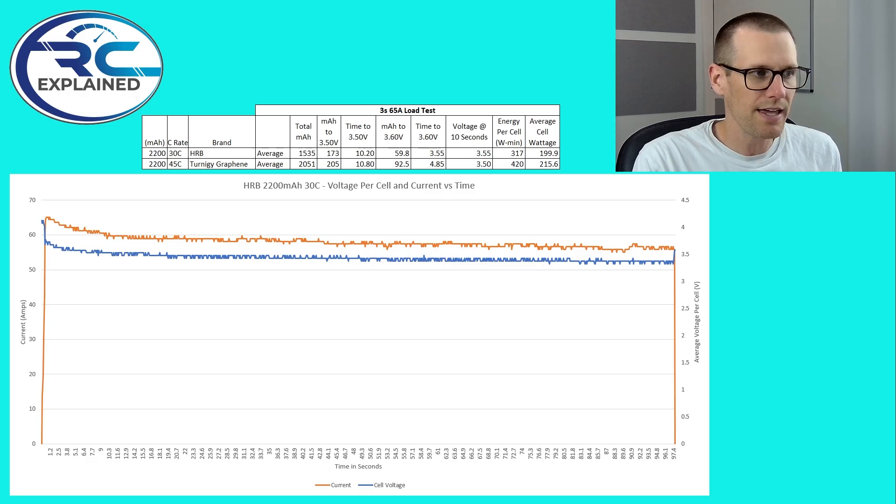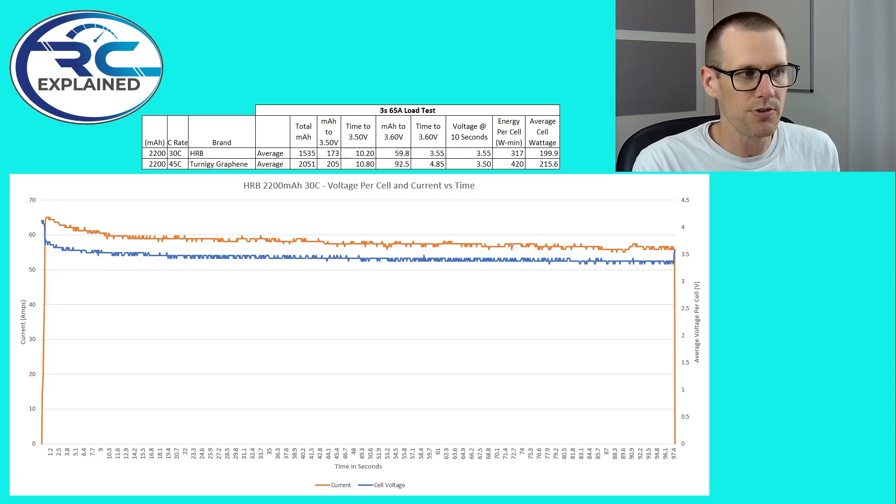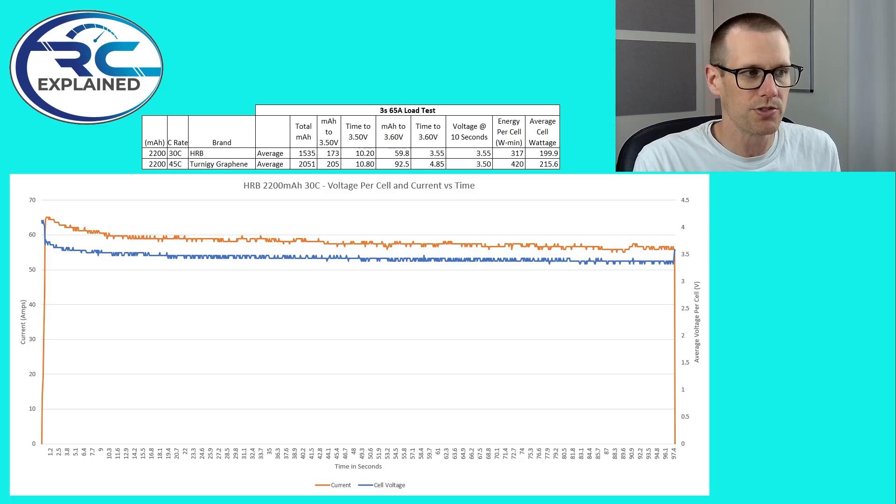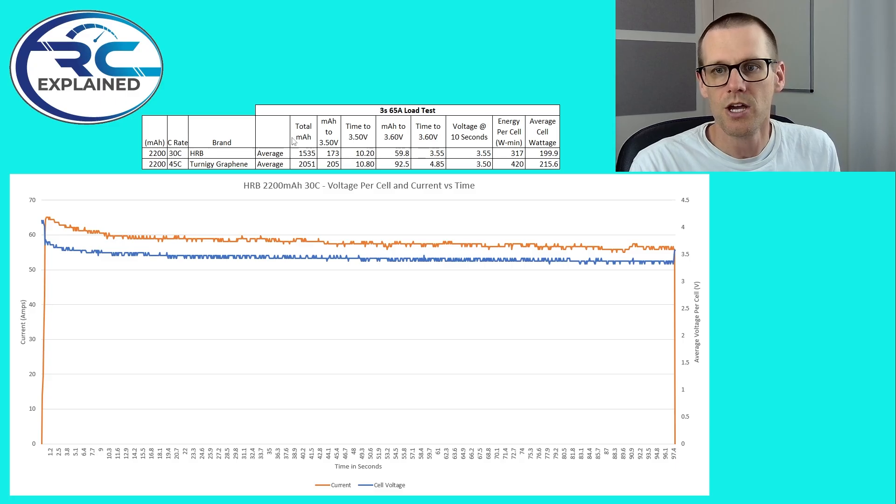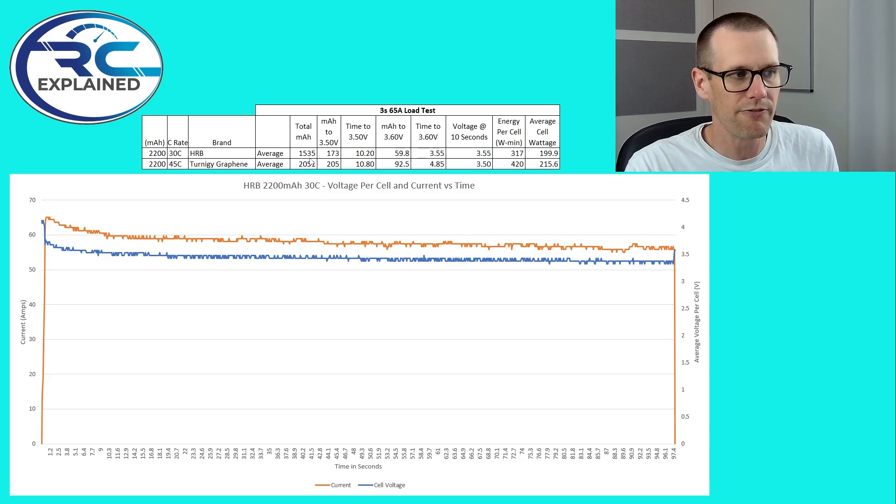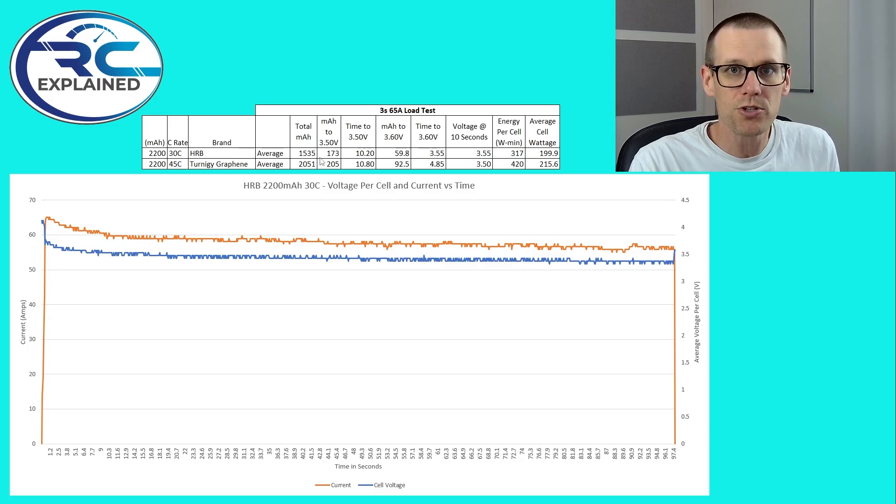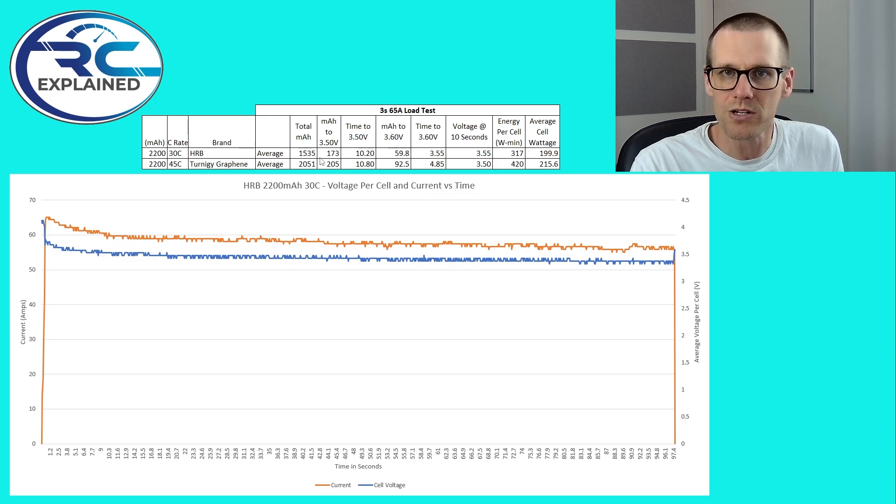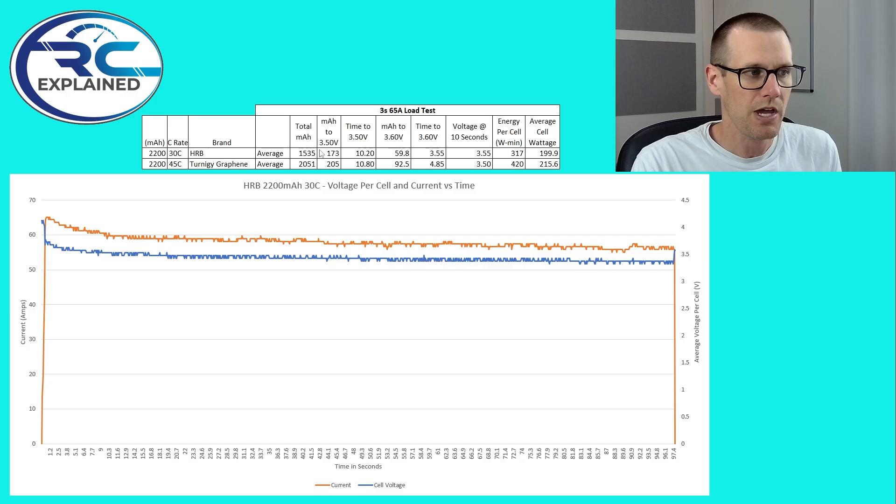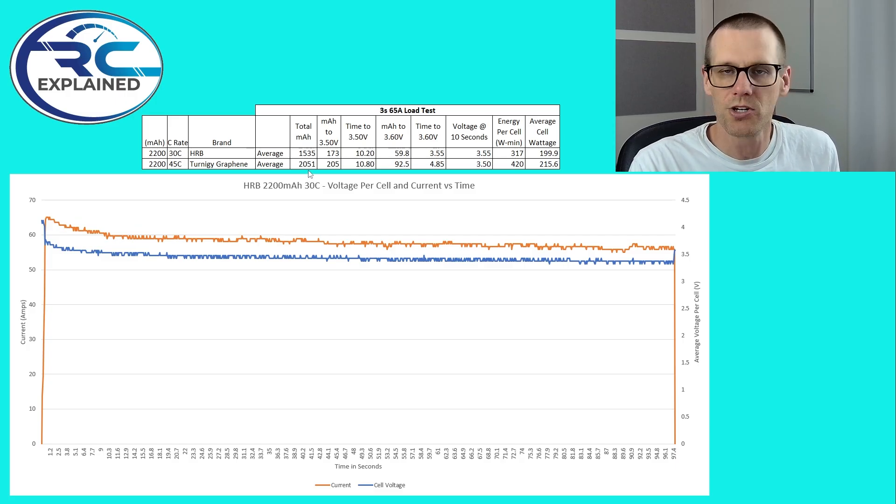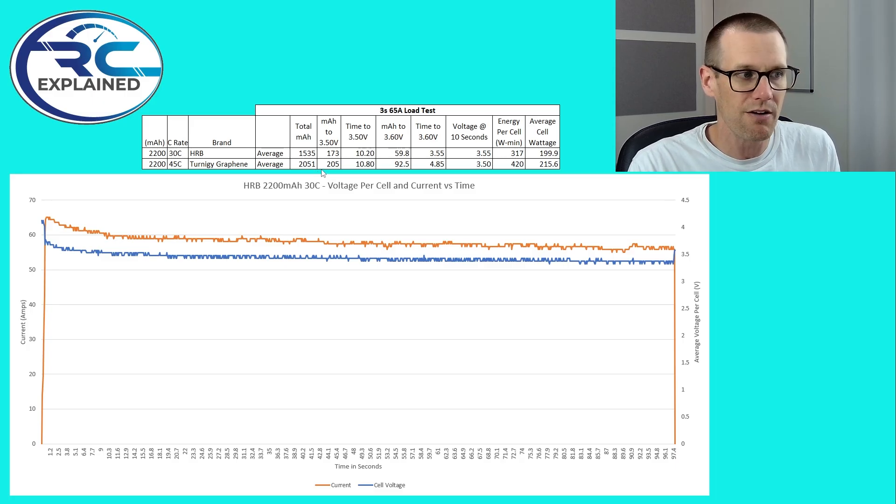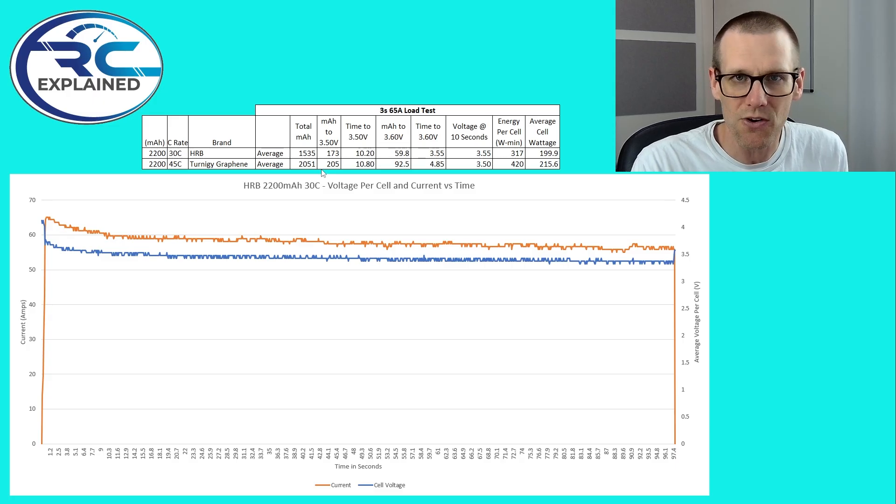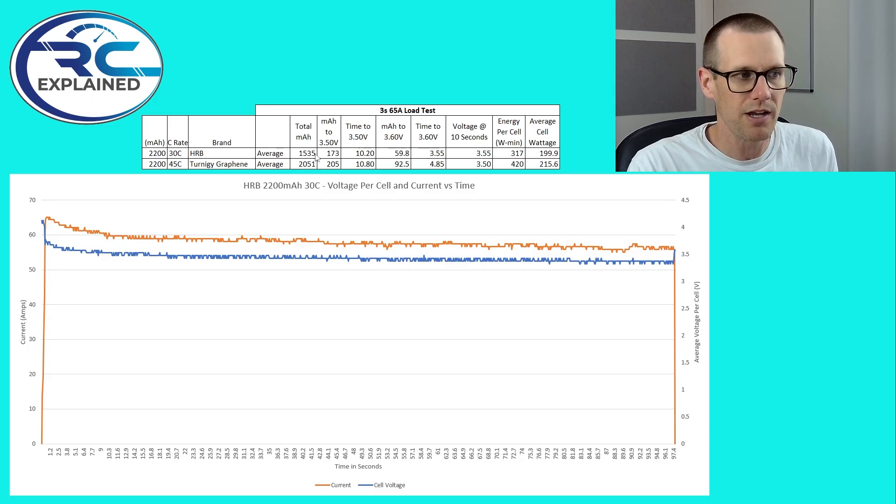Here's the data that we've collected for the HRB. I'm going to quickly run through this. It's very similar to the last set so if you've seen the videos and how we do this before you're going to understand what we're going through. So the very first thing that we're going to look at is the total milliamp hour that the HRB delivered. HRB delivered 1535. This was an average for both of the trials that we did meaning the pack with the higher internal resistance and the pack with the lower internal resistance. So they averaged out to this value in comparison to the Turnigy. The Turnigy delivered 2051 which is a much better number. Delivering that kind of capacity for a 2200 milliamp hour pack is a very good value for the Turnigy. Excellent battery there.